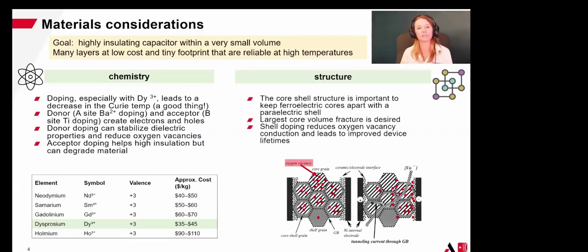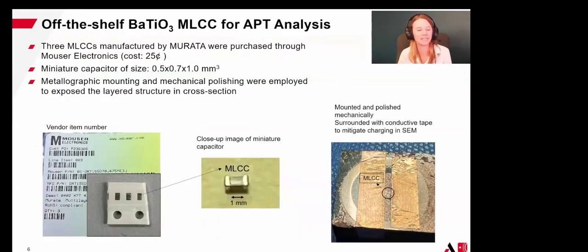Another piece of this is the structure that forms on MLCC synthesis, which is a big contributing factor to the operation of the devices. What we're really after here is a core shell structure where we have a ferroelectric barium titanate core and a paraelectric doped shell. The idea here is within that ceramic layer, we have a number of these different core shell structures in 3D with the largest amount of insulating core volume that we can, but a uniform shell that can limit oxygen vacancy diffusion between cores. And so, as you might imagine, with both doping questions and structure questions, the atom probe is a really good technique for MLCC research.